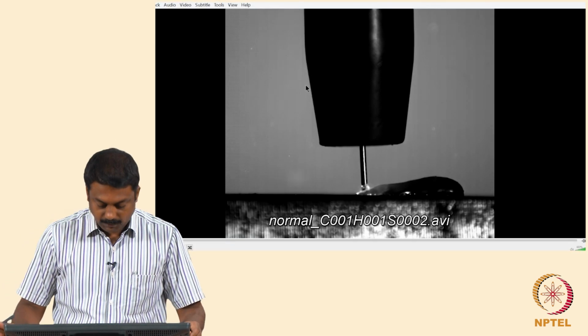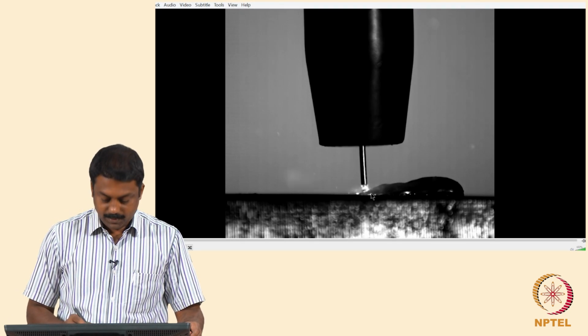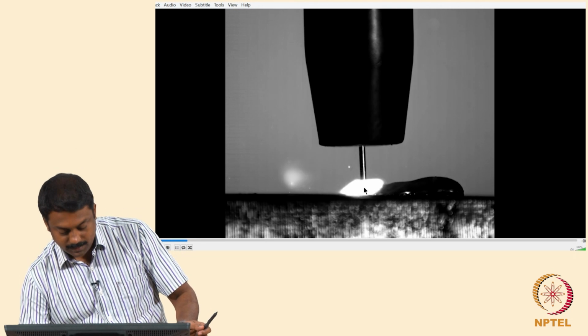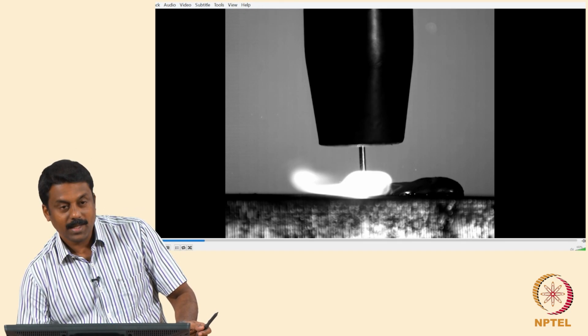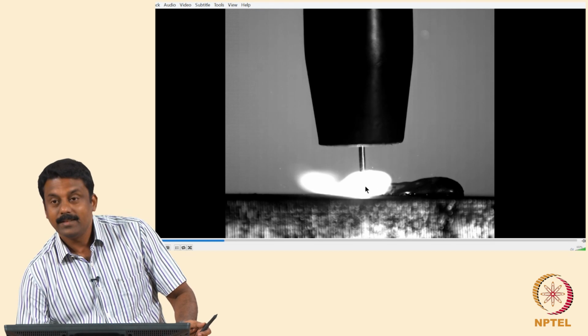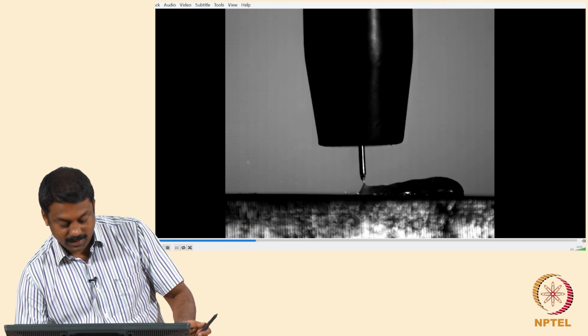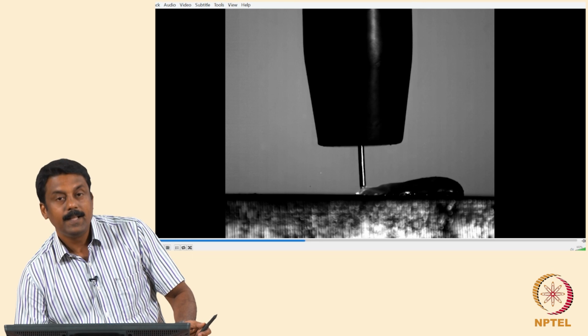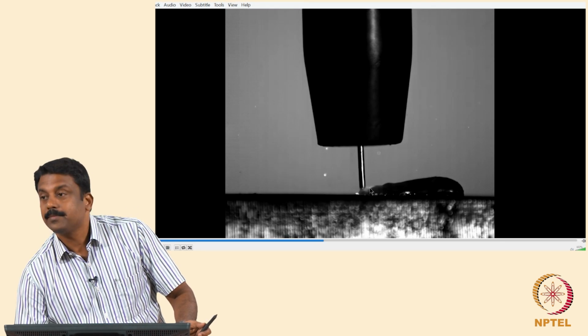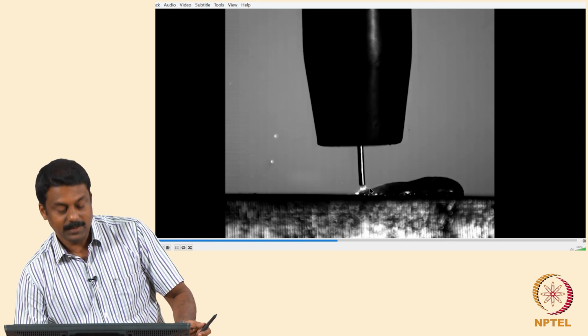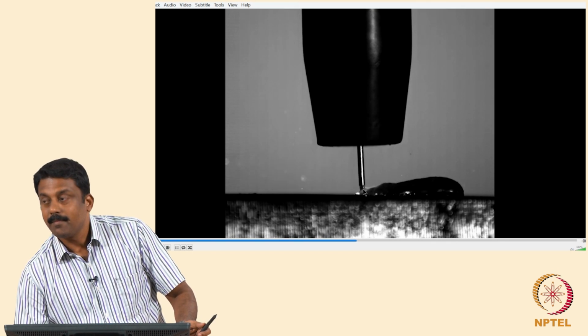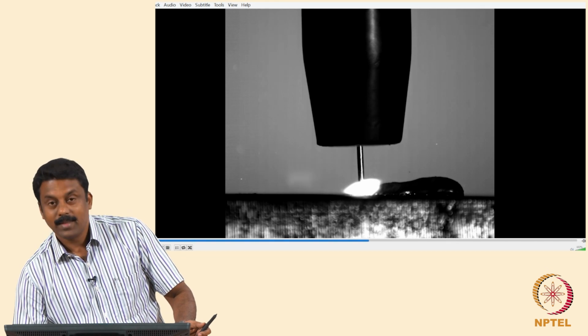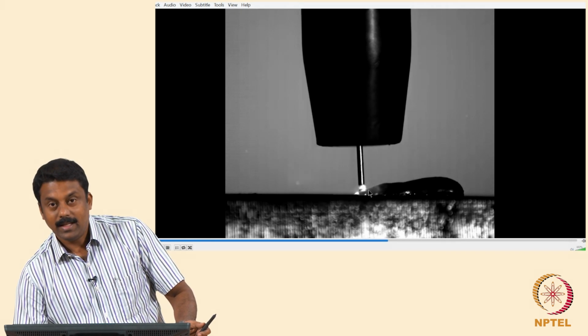So, you see the transfer. So, what is happening here? So, you have an arc. So, transfer happens by the short circuiting, and during the short circuiting event there is no arc. You see that? So, you establish the arc with an arc length, and then you switch off the arc the moment the short circuiting happens, and then you transfer the droplet by the surface tension of the liquid pool. Yes, it's clear? So what is the explosion? The explosion is the arc. Okay, so it comes after the short circuit.